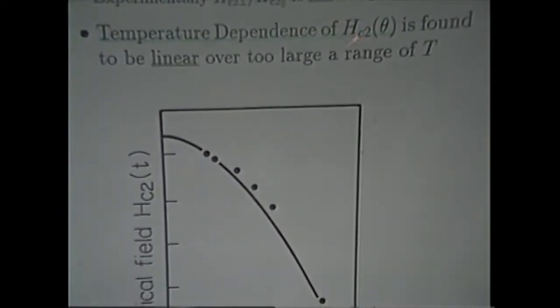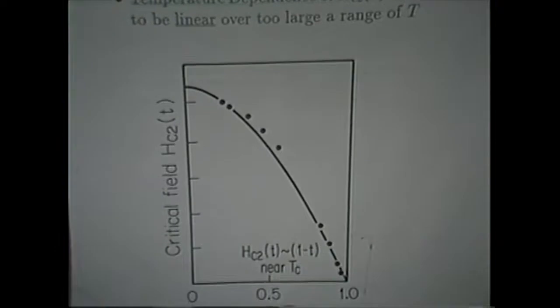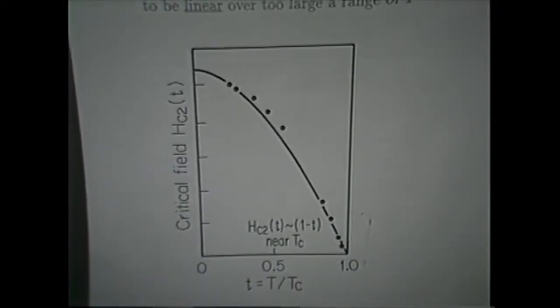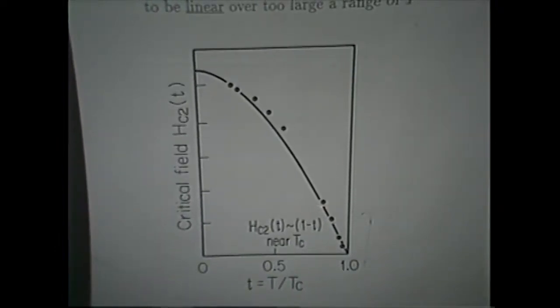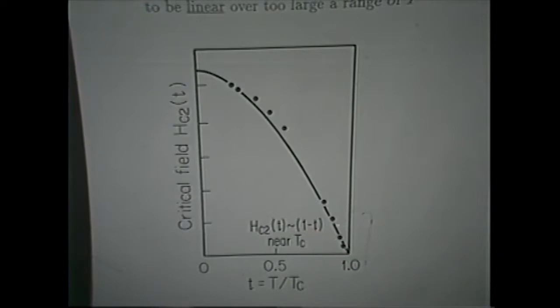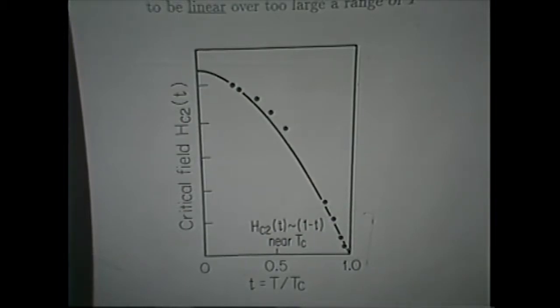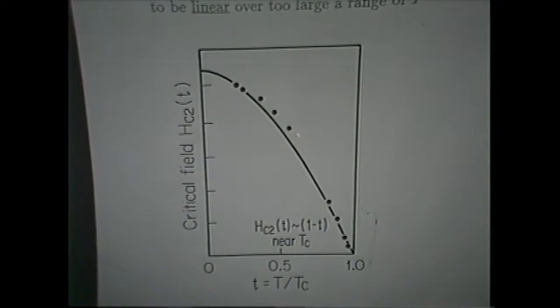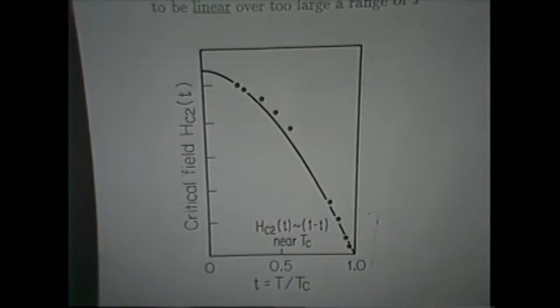It's supposed to be independent of temperature, but experimentally, it's found not to be. Also, the temperature dependence of HC2 doesn't follow this mean field value. This mean field curve predicts that HC2 should have a linear dependence on 1 minus t, where t is the reduced temperature, close to the critical temperature. But by the time you're at little t equal to 6/10, you should start seeing significant deviations from the linear dependence. So in these two respects, the intercalation compounds show significant departures.